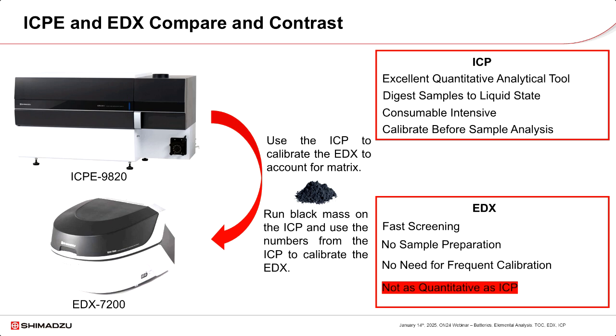Comparing EDX to ICP, EDX is useful for applications like fast screening. There's very little to no sample preparation, and there's not as much of a need to calibrate. Curves last a long time on an EDX compared to an ICPE. The downside of EDX is it's not as quantitative as ICP, namely because you are measuring samples in their native state. So competing matrix effects can become prevalent in EDX compared to ICPE.